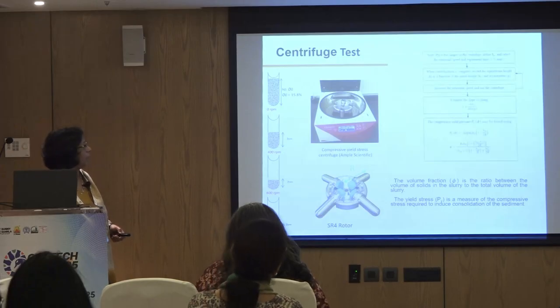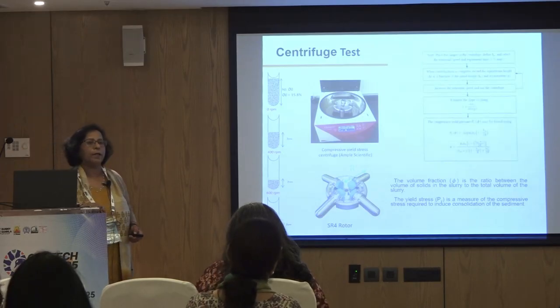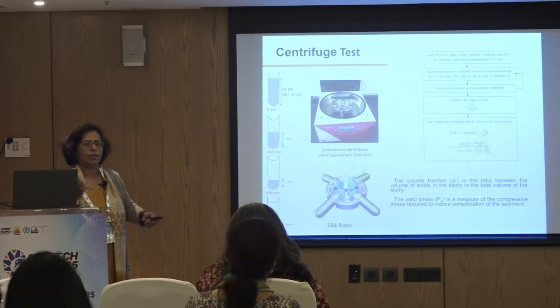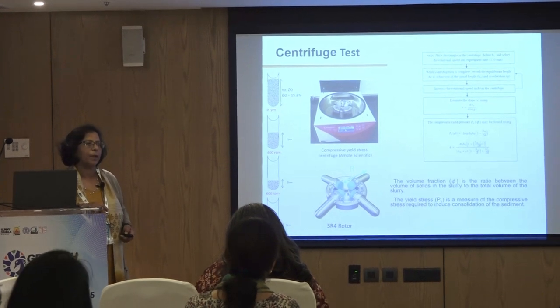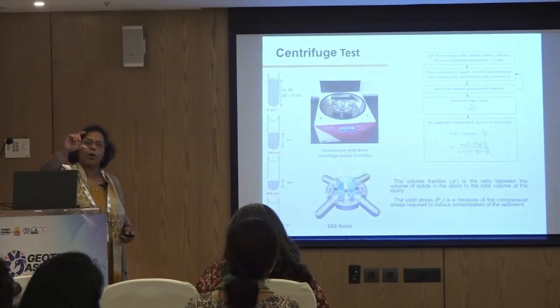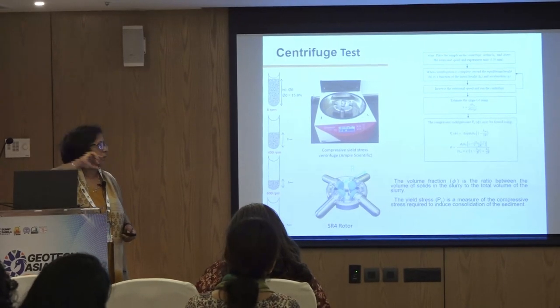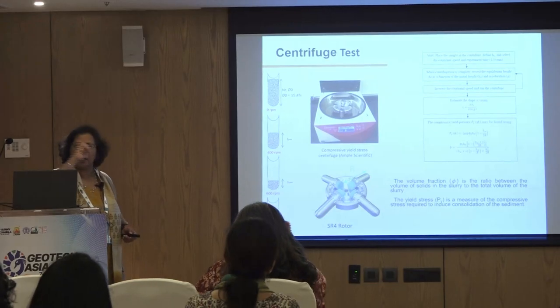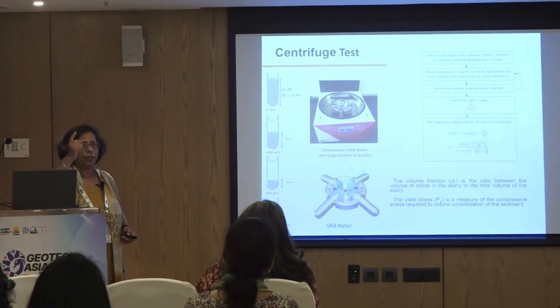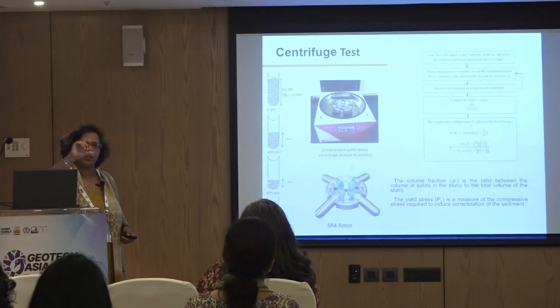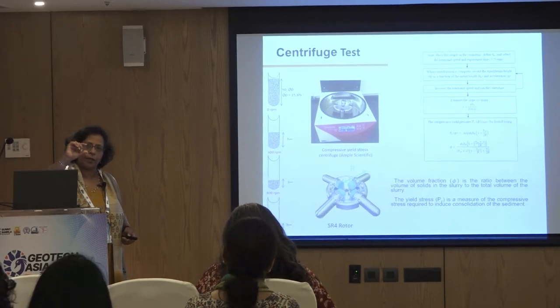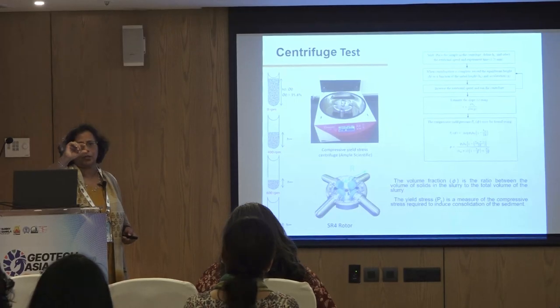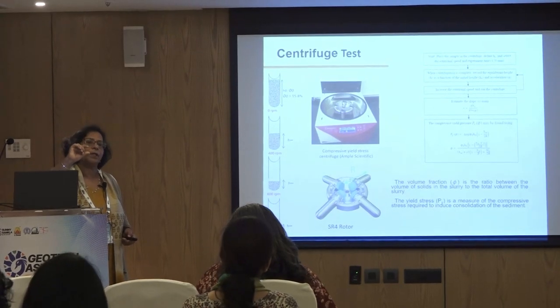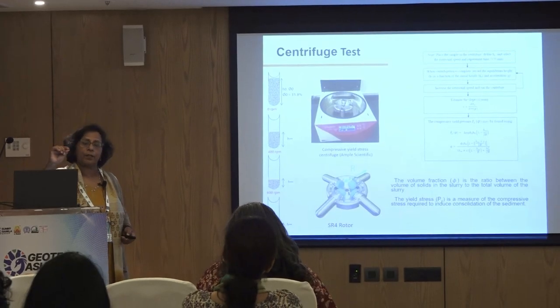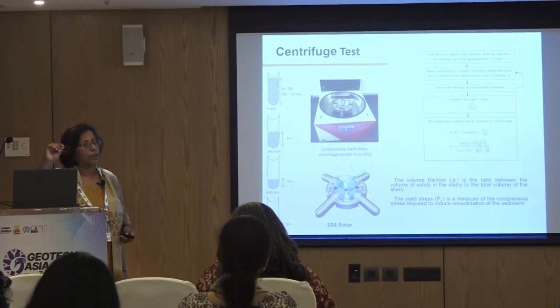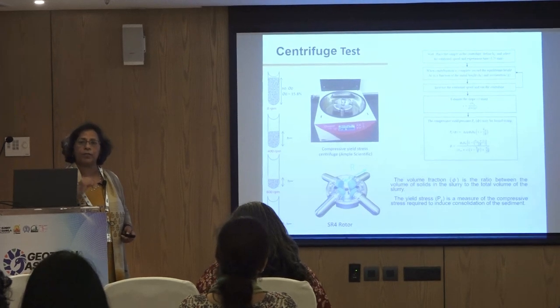One of the tests we have developed over time is called a centrifuge test. This is a very standard test used in chemistry or chemical engineering, where you take a small bottle of slurry, put it in the centrifuge, and rotate it at very high frequency and rotation. After that, the height decreases as the sediments consolidate, and then you measure the consolidated height. And from that, we predict what will be the solid content. And we have found